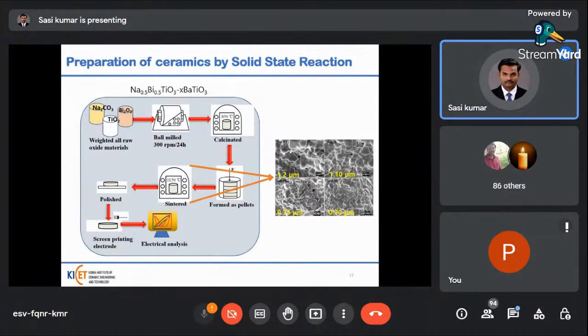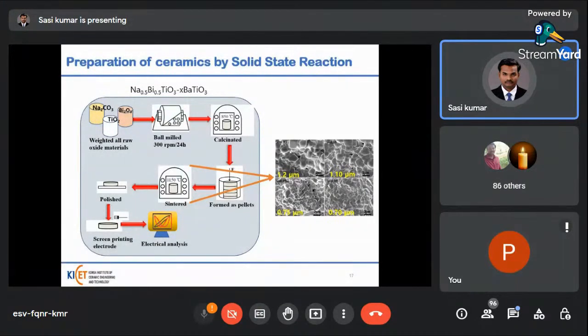So at the calcination, the three raw compounds are mixed and it forms the composition sodium bismuth titanate modified with barium titanate. The barium atom occupies the A site of the ABO3 structure, and the titanium atom is the B site of the ABO3 structure. And then the final sintered pellets have high density.